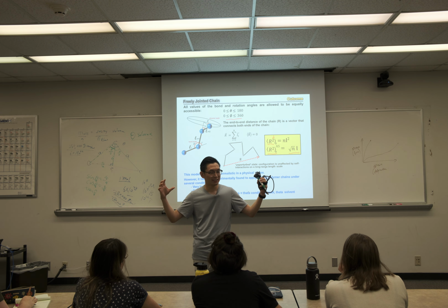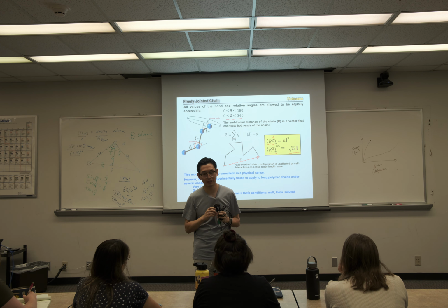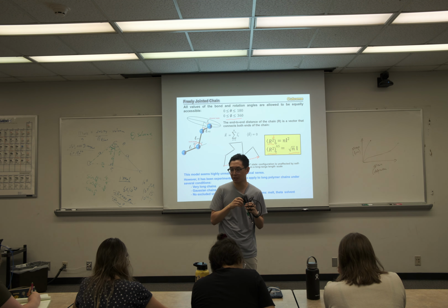So going from 25 to 5, the solvent can be just slightly bad such that your polymer chain end-to-end distance happens to match a 3D freely jointed chain. Okay? Does that make sense? So the theta solvent, in between good and bad solvents, forces your polymer coil to collapse to the dimension of a freely jointed chain.